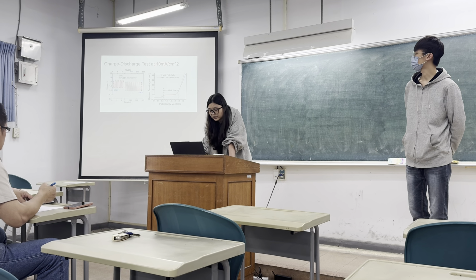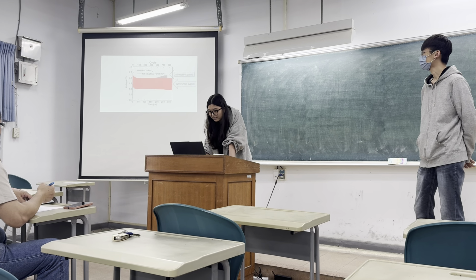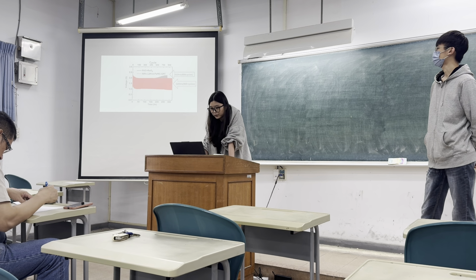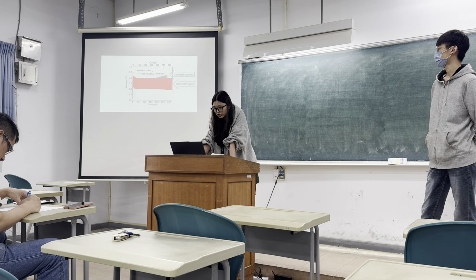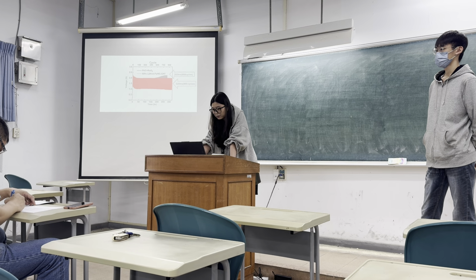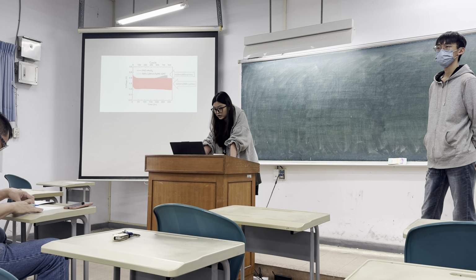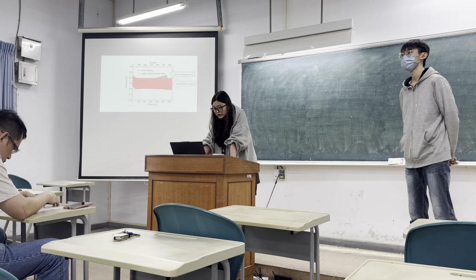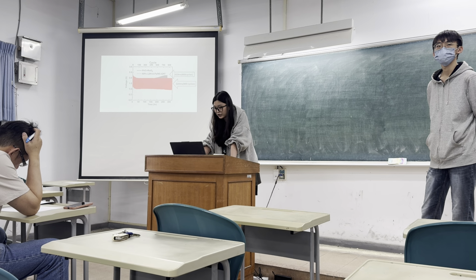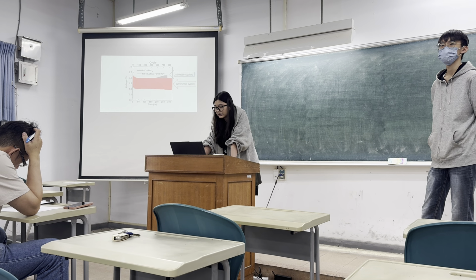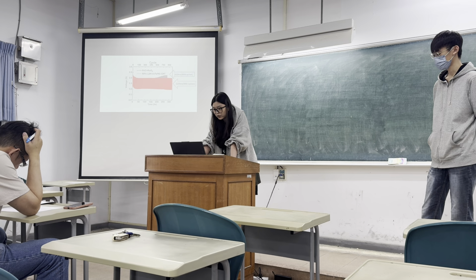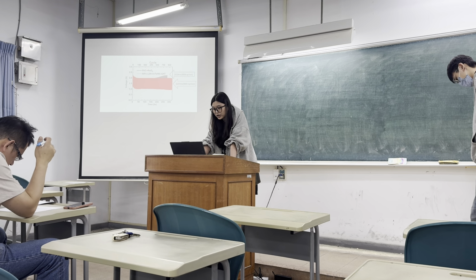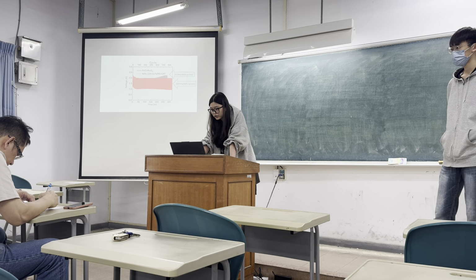So they're matched. And this is the long-term test result, shown in this picture compared to commercial catalysts. Our liquid zinc-air battery has better stability and lifespan. The test ran for 69 cycles, and we can say